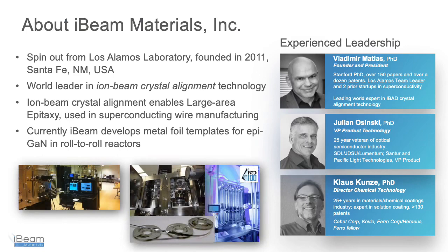Our company, iBeam Materials, was started about 10 years ago as a spin-out from Los Alamos National Laboratory and is located in Santa Fe, New Mexico. We're the leaders in ion beam crystal alignment technology, where one deposits a film with an ion beam during deposition, which allows us to align the crystallites in the film during growth. This is a way to make large area epitaxy.